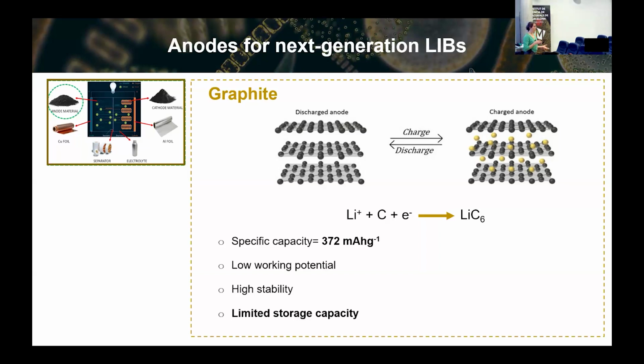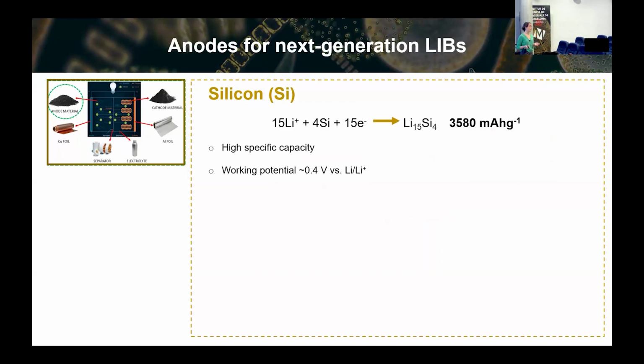So there are two approaches to tackle this issue. One is just to introduce some higher energy density material to graphite, or just to change the anode material from scratch. So one of the alternative materials to graphite is silicon. Silicon has a theoretical capacity that is 10 times higher than graphite. But the intercalation between silicon and lithium ions is totally different, and is via an alloying-de-alloying reaction. So when lithium reacts with the silicon, the silicon will expand quite a lot to form a lithium silicide phase. And when the silicon is delithiated, it will contract. And this expansion and contraction is about 300%, not 8%.